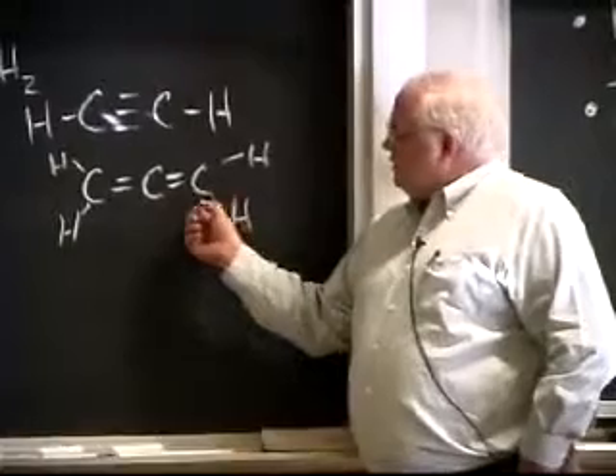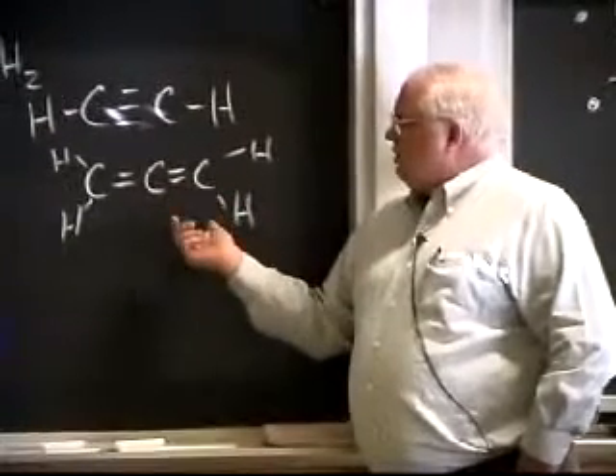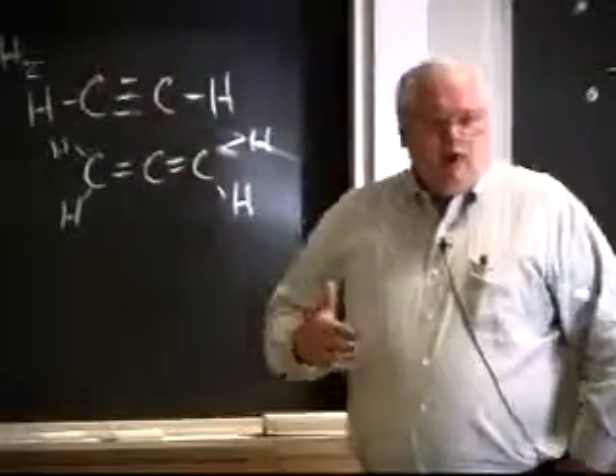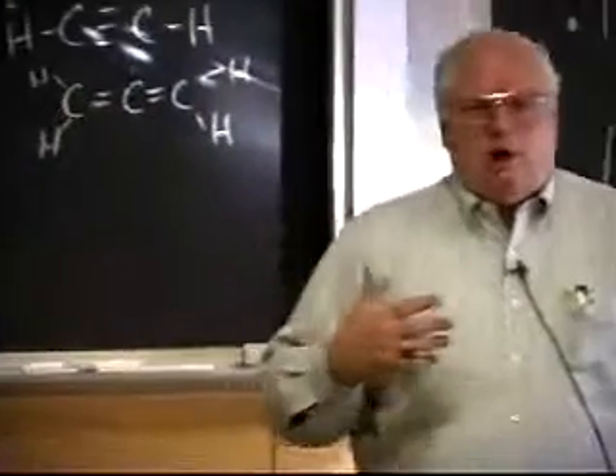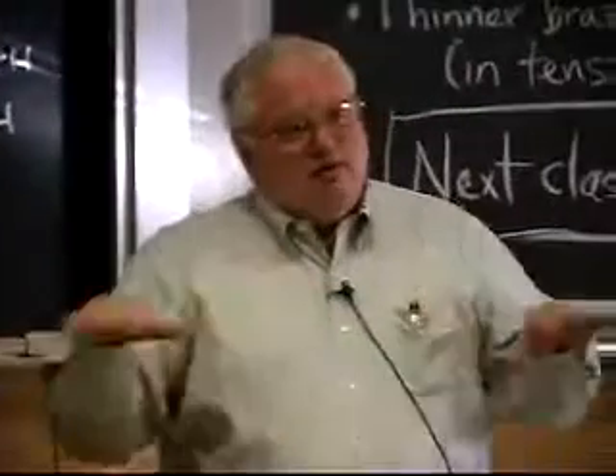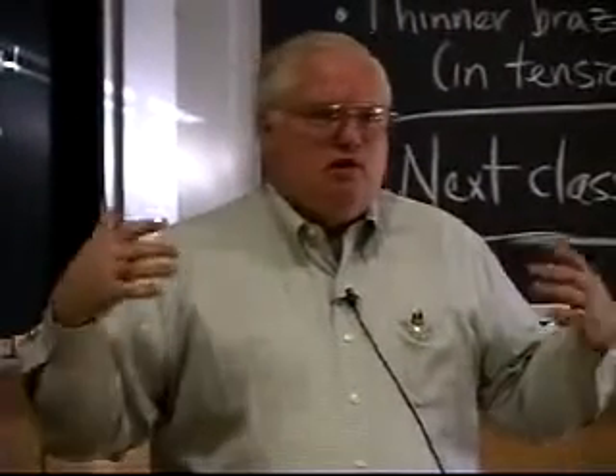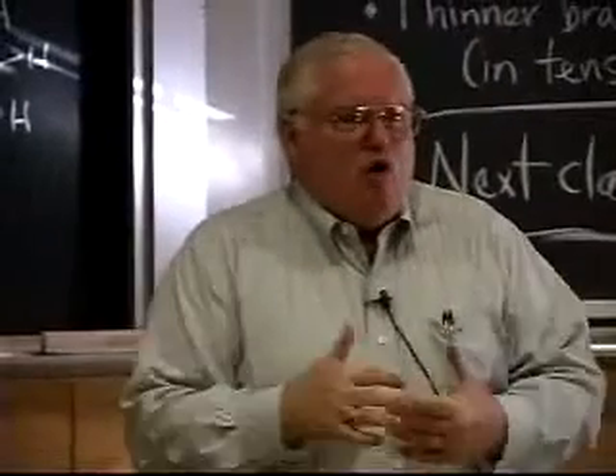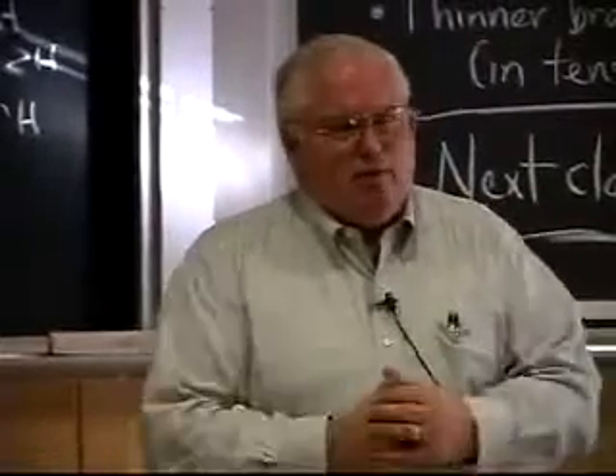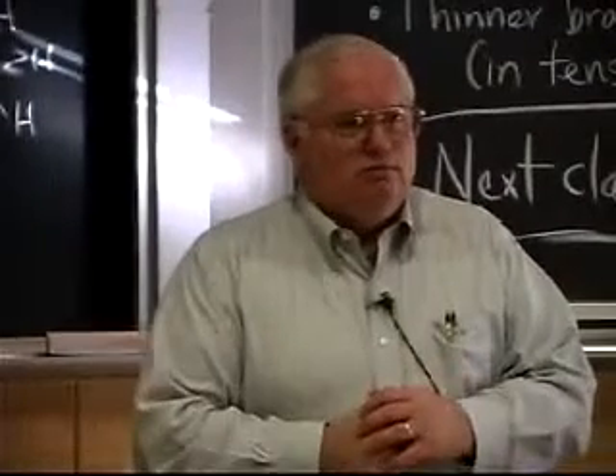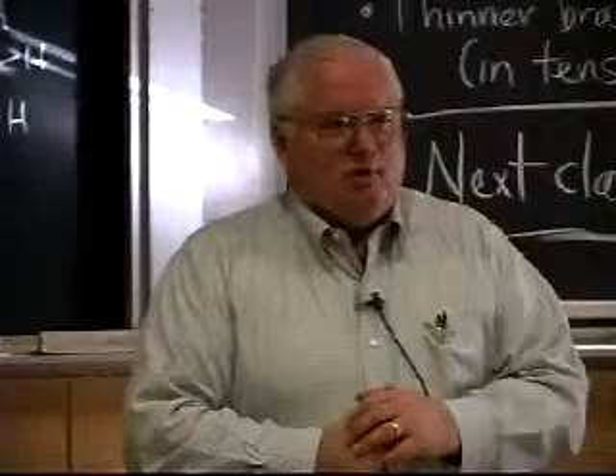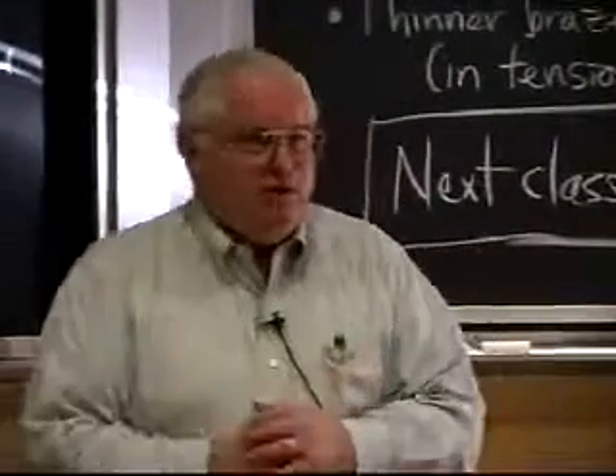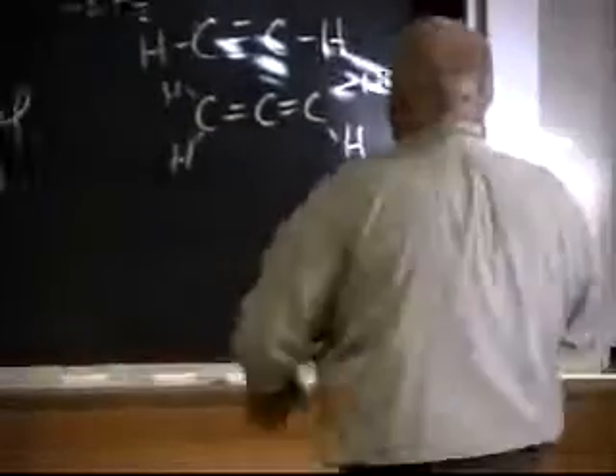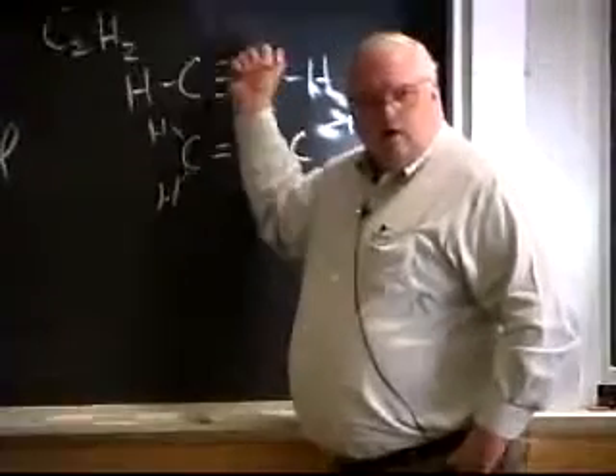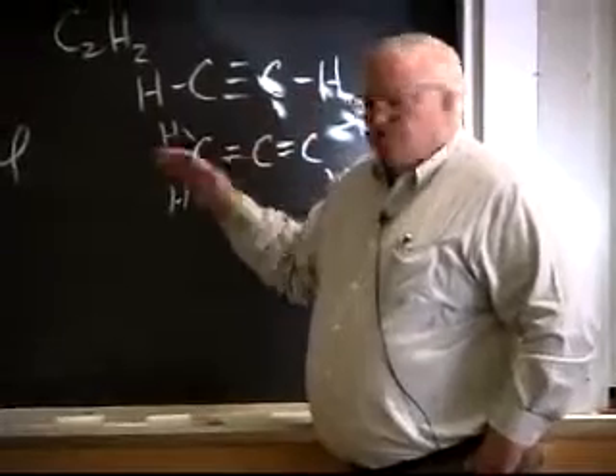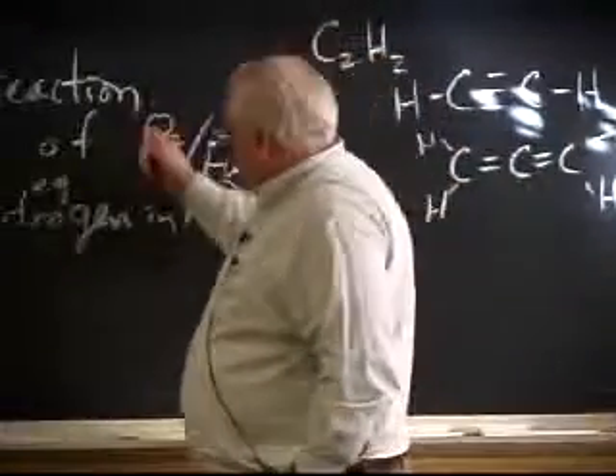This is propadiene, which is basically C3H4. And it's got a fairly high, but basically as you go to bigger and bigger, more complex hydrocarbons, they all start averaging out to the same thing. Gasoline per carbon atom doesn't have a whole lot different energy content, BTUs per pound, if you will, than does polyethylene. Or you can go to a very heavy hydrocarbon, tar. You know, it's harder to pump the tar unless you get it hot. But basically, acetylene has, I think, about a 30% higher BTUs per pound than most of your other garden variety hydrocarbons. So you want a good enthalpy of the reaction.